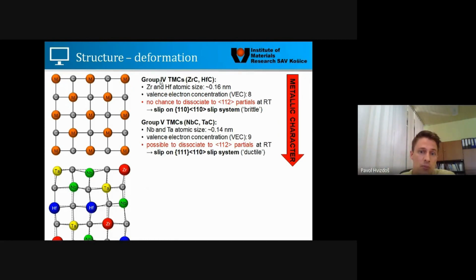We have group 4 transition metal carbides. In our case, it was only zirconium carbide and hafnium carbide. Of course, titanium carbide is also in this list. They have a relatively bigger atomic size compared to group 5, and they have a valence electron concentration of 8 because they are in group 4. And for those materials, there's no chance to dissociate to specific partials at room temperature.